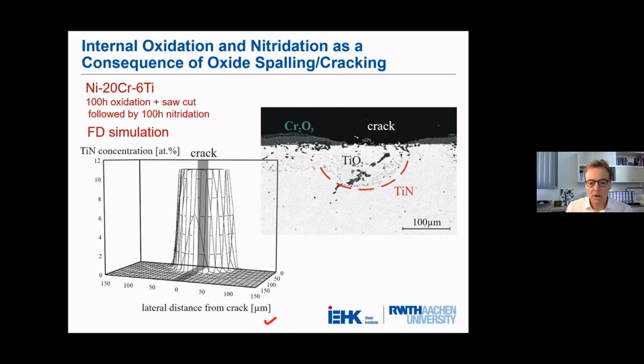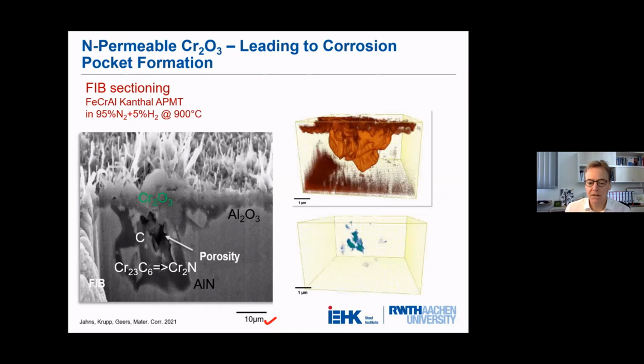Well, obviously, chromia is permeable to nitrogen. It does not protect against nitridation, and that is manifested by the next example, where we found a complex corrosion pocket. That is opened up by means of focused ion beam sectioning. Here we have locally a chromia scale in the vicinity of a chromium carbide, and the carbide is then transformed to chromium nitride. We also get aluminum nitrides and the formation of carbon. The idea is that we get a reaction of the carbon with hydrogen from the atmosphere, and then a very high pressure increase that opens up this kind of porosity. Here you see this in 3D. That is the complete corrosion pocket, and that is this pore formation.